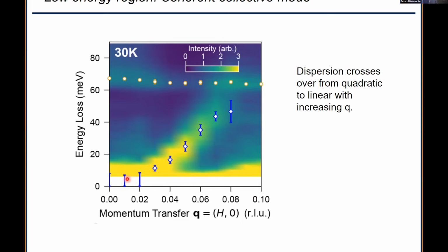We didn't know what it was, but gapless modes are a sign of a Fermi liquid. So this is what you expect: collective excitations that propagate well, response functions that are Q dependent. So we wrote a paper and submitted it and said at low energy, it's clearly a Fermi liquid. There's a Fermi liquid-like mode, and then there's a crossover to high energy where it acts like a strange metal, which is sort of what you would expect based on the transport.